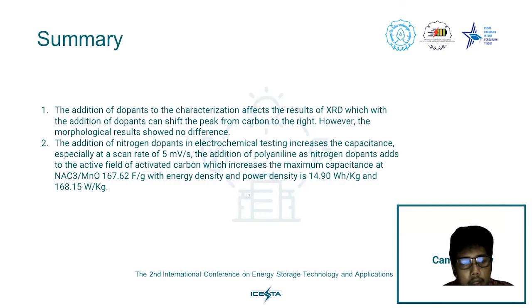And then for the summary, the addition of dopants affects the XRD result, in which the addition of dopants can shift the peak of carbon to the right. However, the morphological results showed no difference. And then the addition of nitrogen dopants in electrochemical testing increased the capacitance, especially at a scan rate of 5 millivolt per second. The addition of polyaniline as nitrogen dopants adds to the active sites of the activated carbon, which increases the maximum capacitance at NaC3MnO, with a result of 167 farad per gram, with an energy density of 14.9 watt-hour per kilogram and a power density of 168.15 watt per kilogram.